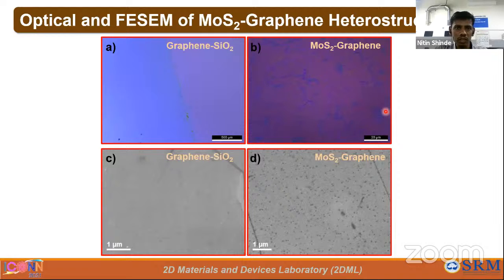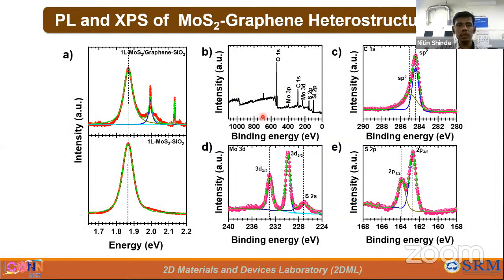This is an optical image of graphene transferred on SiO2 substrate, and this is the MoS2 deposited on graphene. This is an SEM image, and this is the MoS2 graphene structure. We can see that we deposited everything, and we also analyzed the PL spectra of MoS2 on SiO2 and the MoS2 graphene structure. We are getting very sharp and high intensity PL spectra on the SiO2 substrate, and the same thing on the graphene substrate. The sharp intensity and small full width at half maximum clearly indicate that our sample is optically very good.